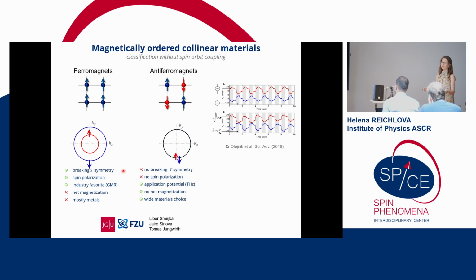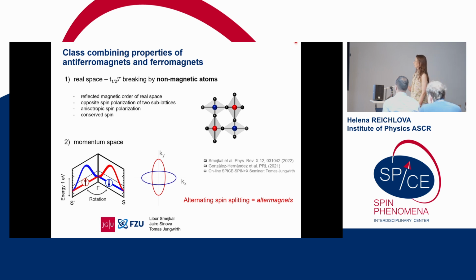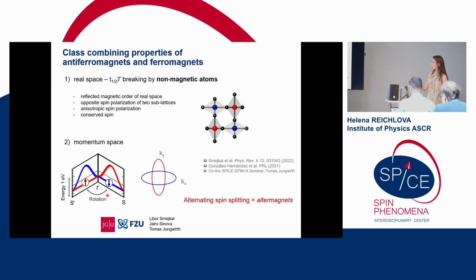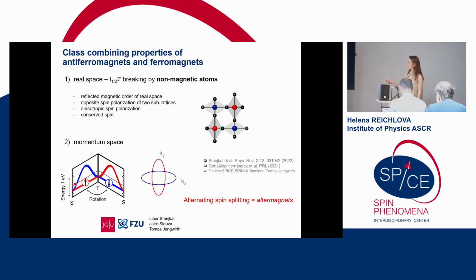And then, as Matthias mentioned, the effort driven by Libor Šmejkal showed that there is yet another class, which is still in the universe of simple collinear systems. And this is just by considering also the non-magnetic environment of such a simple square lattice. By these anisotropic oxygen cages, which are not connected by inversion or translation, but by rotation in real space, it translates to momentum space as the splitting of the electronic bands with opposite polarization in such a fashion. And when we look at these 90-degree cuts, we see that the spin polarization is alternating, leading to the suggested term altermagnets.